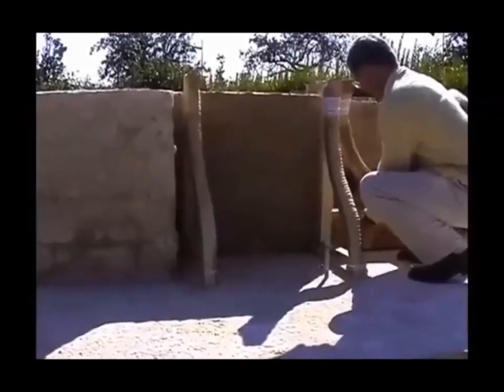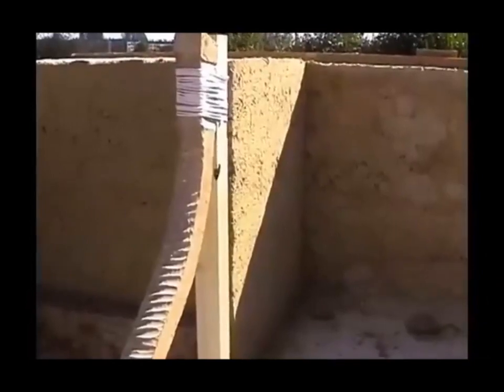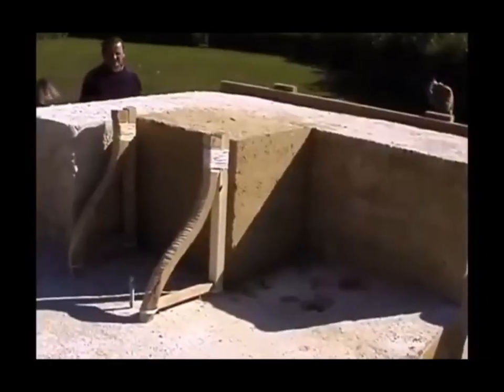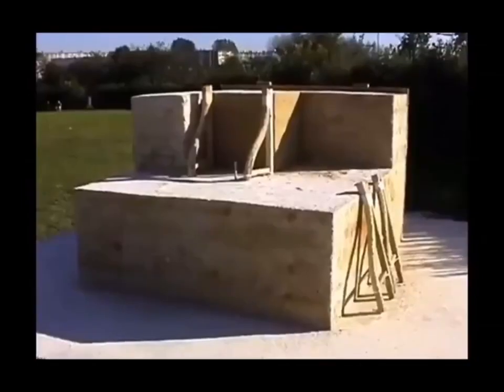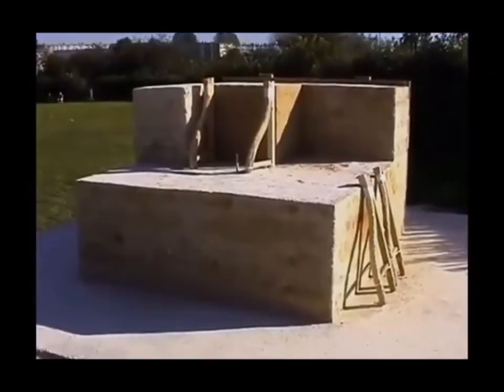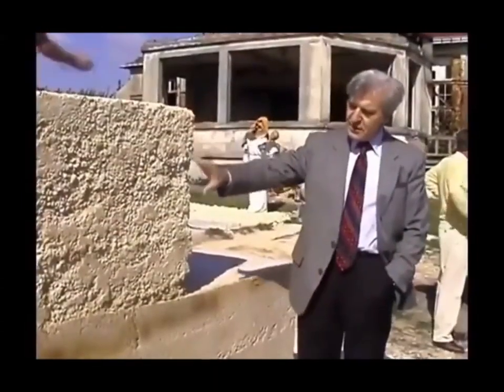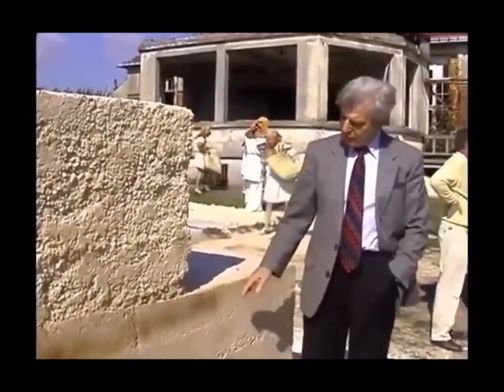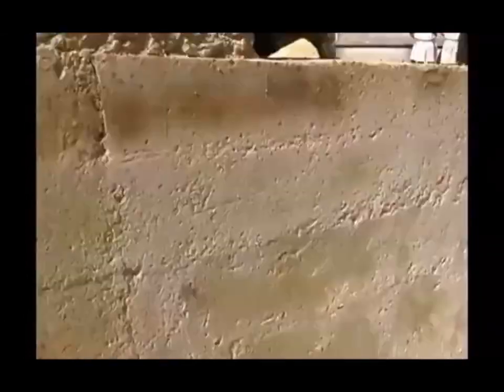The synthetic limestone looks like a natural stone. We observe no trace of wood grain. 4 blocks have already been made. Joseph Davidovits presents them. The 2 large blocks weighing up to 4.5 tons, containing most water, have given smoother surfaces. The 2 small blocks weighing up to 1.3 tons, the least wet, take on rougher surfaces.